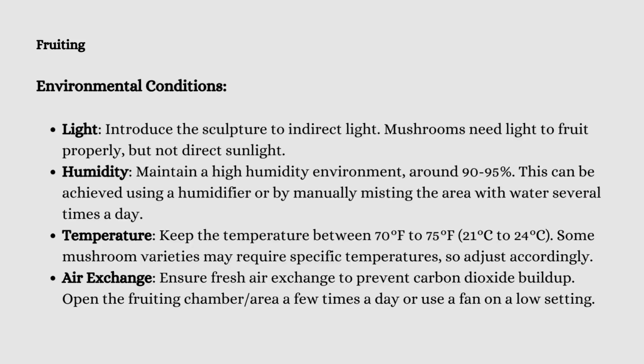And then humidity: you want to maintain a high humidity environment of about 90 to 95%. You can use a humidifier, or you can use this DIY method that we talked about earlier with the aquarium heater in a large glass vessel holding at least a liter of water, if not more, because that water will evaporate.